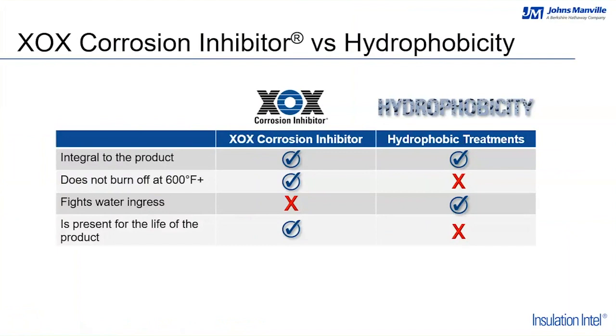So if we look at the attributes, first off is the XOX corrosion inhibitor and most products that are hydrophobic, that is integral to the product. The XOX product will not burn off in applications that go above 600 degrees, where the hydrophobic product will burn off at elevated temperatures over 600 degrees. While the XOX does not fight water ingress, the hydrophobic product does, but the XOX is present for the life of the product. So it's going to be there from installation until the product is removed, while the product that is hydrophobic may or may not. So the life of the hydrophobic agent is going to be dependent on the temperature that the product sees over its lifetime and the time at that temperature.